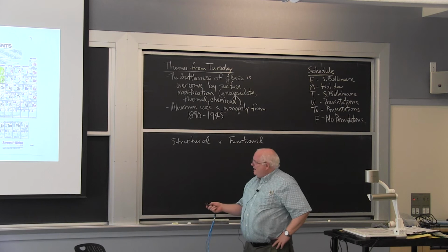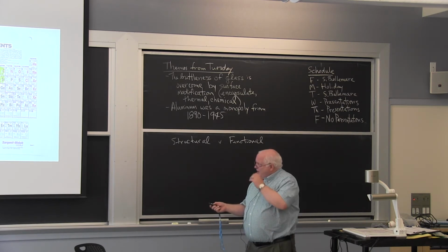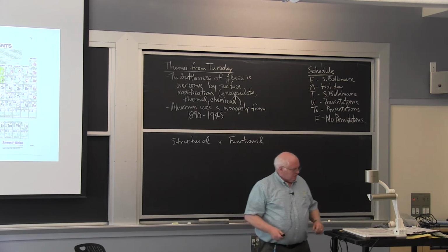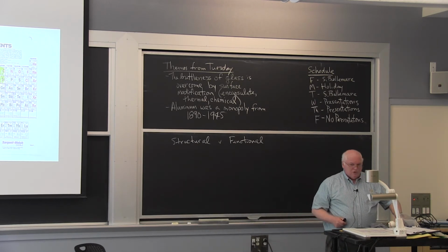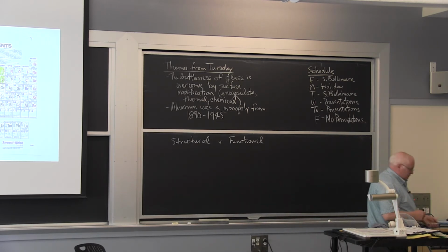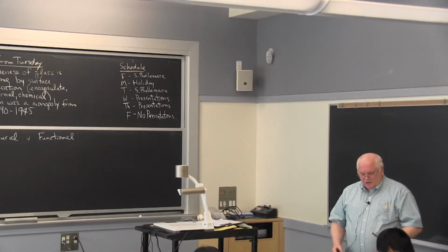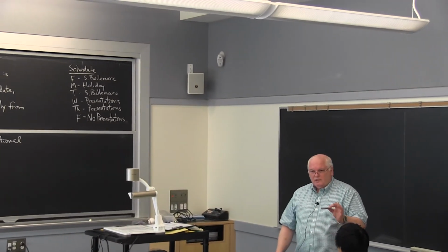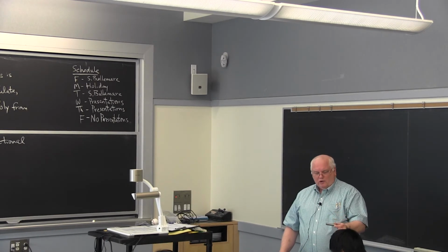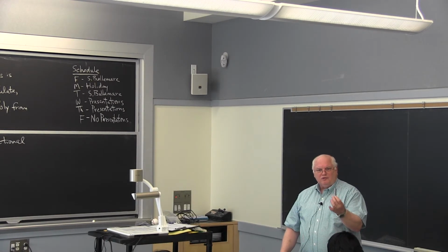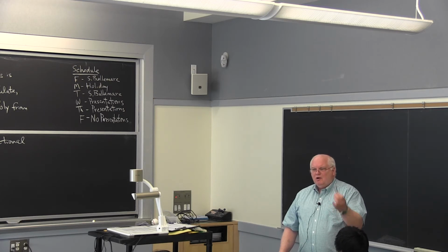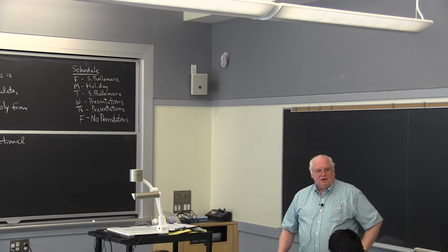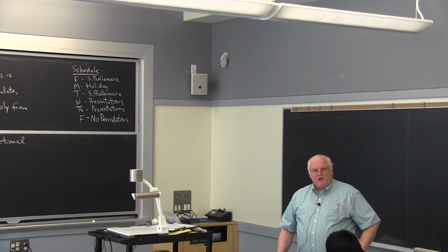Now, titanium, zirconium, and hafnium. Well, titanium we already know about. Zirconium is a structural material in a very special application. Anybody know what? This is crystal bar zirconium. You can tell it's fairly heavy. It's made by reducing zirconium tetrachloride on a hot wire of zirconium, and it just grows from the vapor phase. This is a zircaloy alloy tube, nuclear reactor fuel cladding. Very low nuclear cross section. Those little neutrons go right through it, okay? And so it won't poison the reaction.